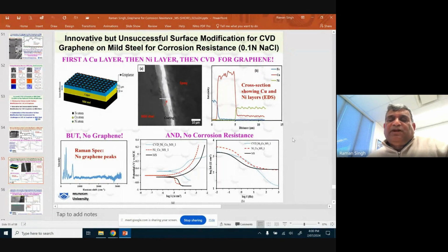So where is the problem? The problem is that carbon dissolving into the nickel layer will diffuse into mild steel. Why don't we put a layer in between which will stop carbon from diffusing to mild steel? And what is that? It is copper. You remember earlier I said that copper has insignificant solubility of carbon. So carbon will be retained in the nickel layer because the copper layer will not allow carbon to diffuse to mild steel. In the absence of copper, whatever carbon was in the nickel will diffuse into mild steel because both have high solubility of carbon, but copper will stop it.